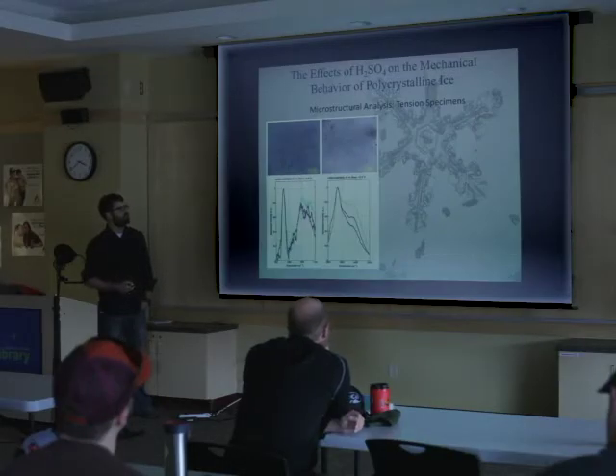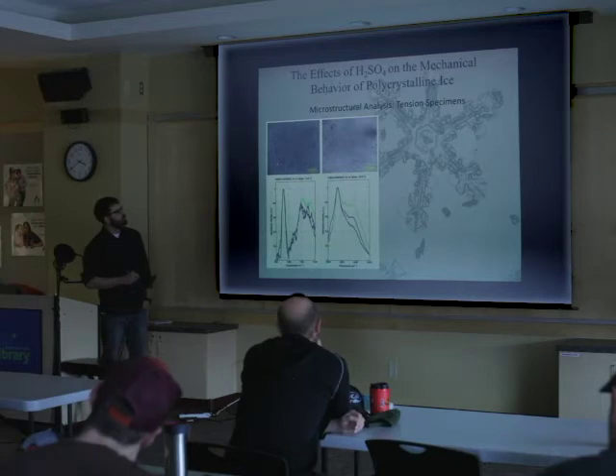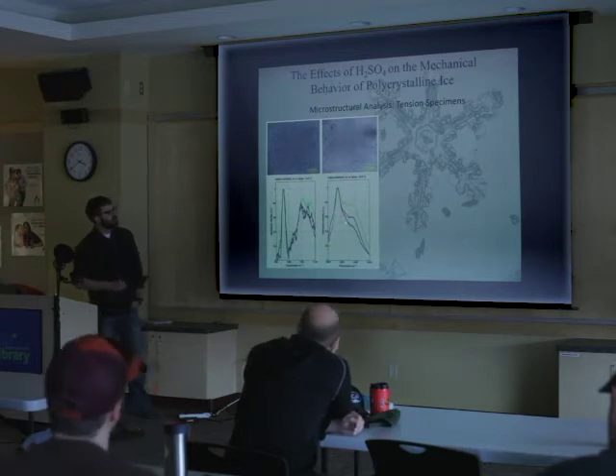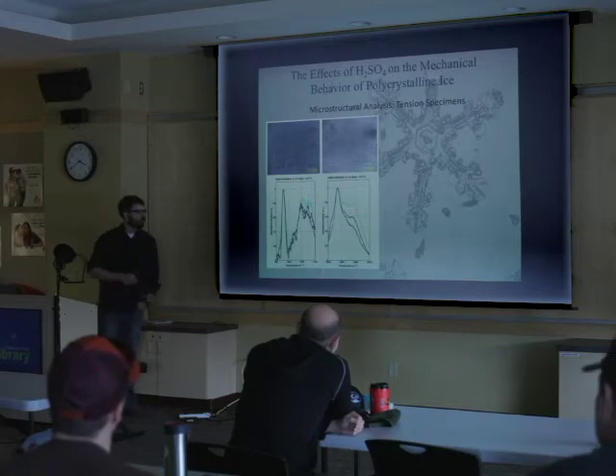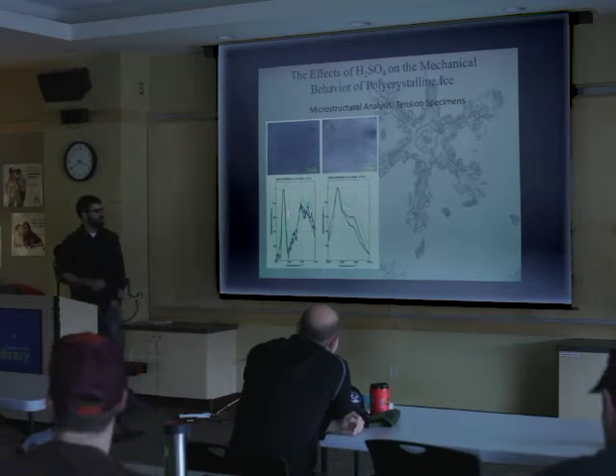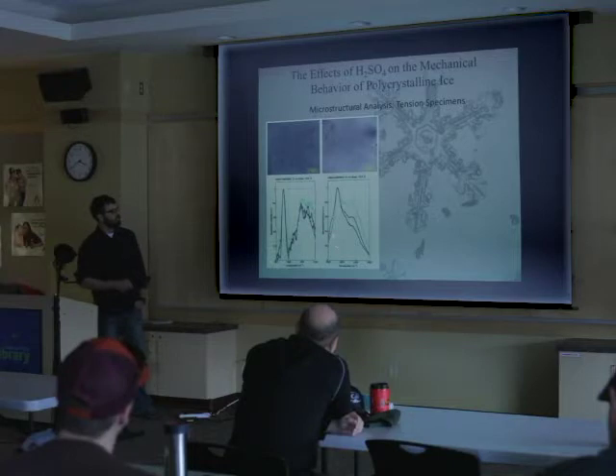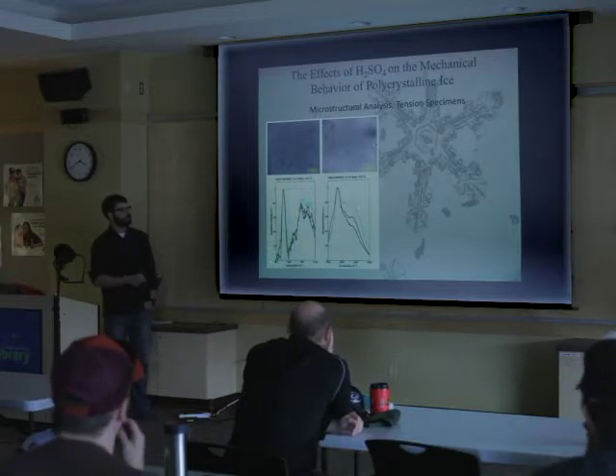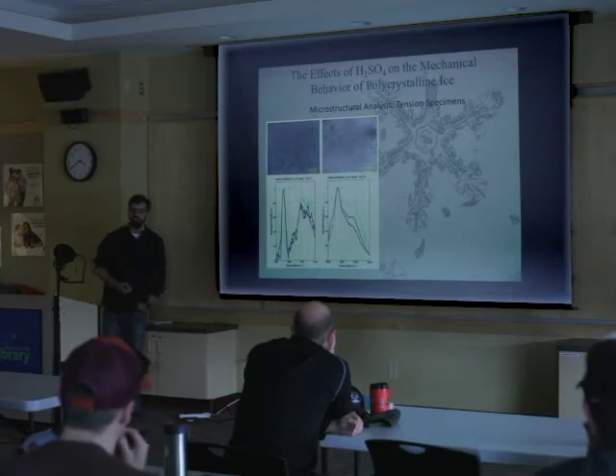So applying this to some of our ice samples, looking at these little triple junctions in the ice, these colored circles correspond to the colors shown here on the plot. This peak shows us SO4, so there's sulfate, which must be bonded to the hydrogen, so you've got sulfuric acid present at these locations. And then you have primarily solid, but you have some differential input here actually from a liquid state.